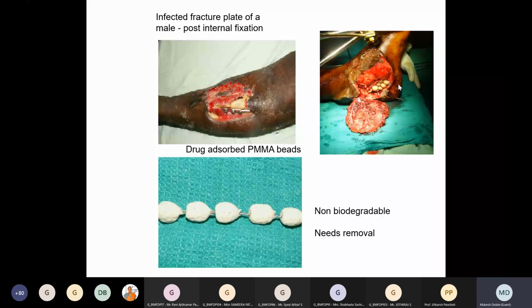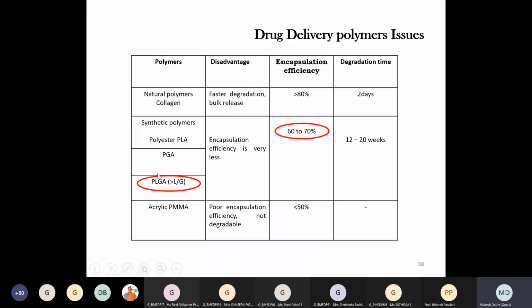It should not cause any adverse reaction to the host, no toxic reaction, and should not lead to any inflammation. So ideally we should have such a polymer. We looked at some polymers approved by the FDA, the Food and Drug Administration, and we ended up with polylactic-co-glycolic acid. The beauty of polylactic-co-glycolic acid is it contains two monomers, lactic and glycolic. Glycolic is more hydrophilic, so it degrades faster. Lactic also degrades, but it's a little more hydrophobic, so it degrades slowly. So we can modify the ratio of lactic to glycolic to get good degradation rates and also good drug loading rates. So we looked at PLGA.